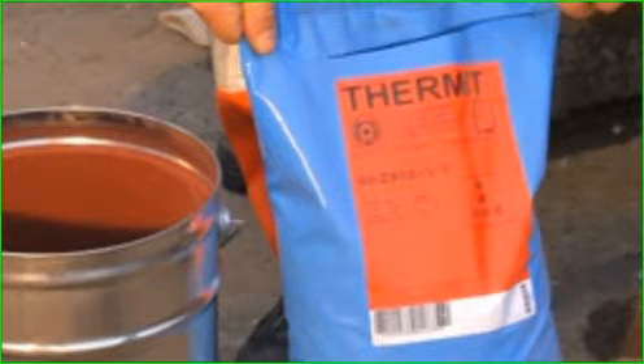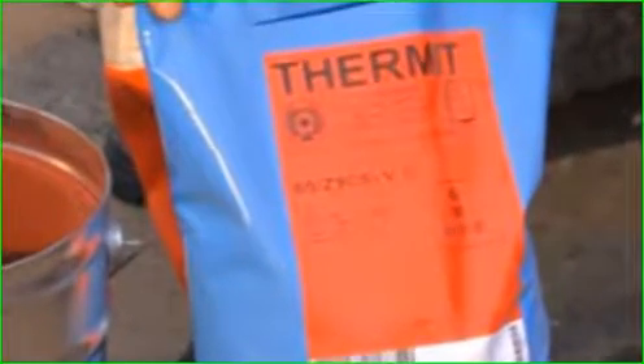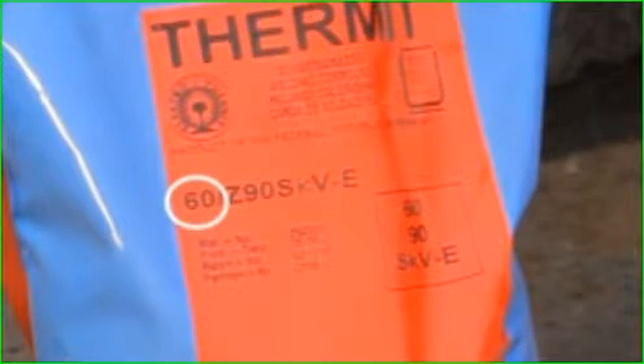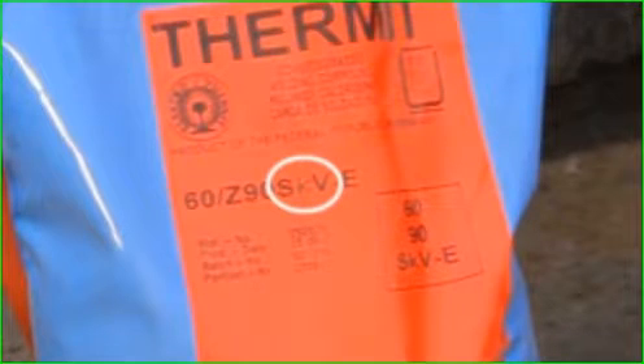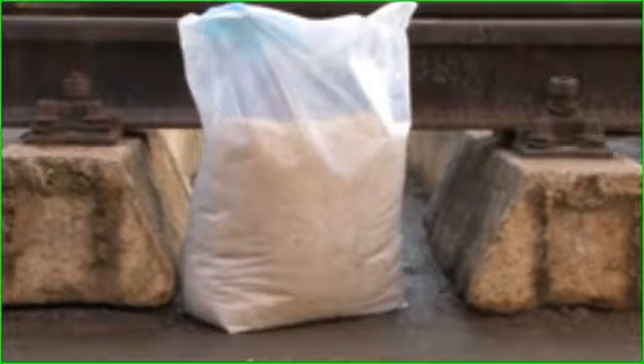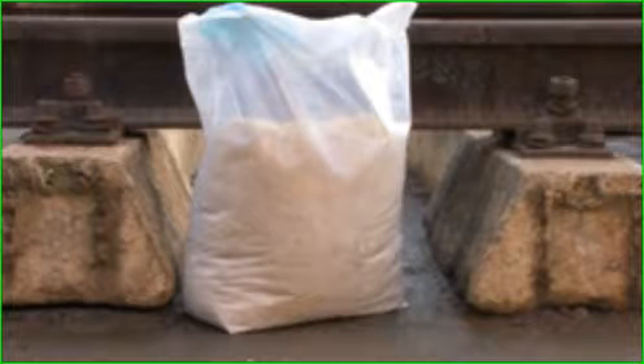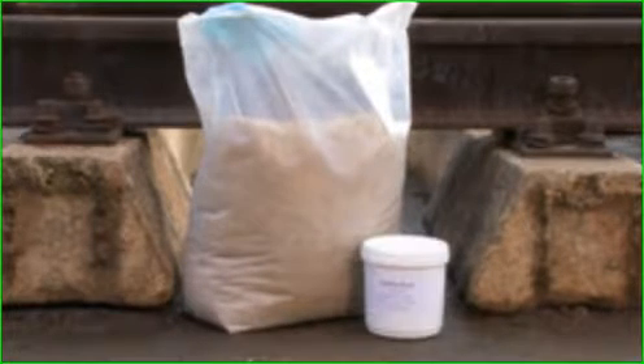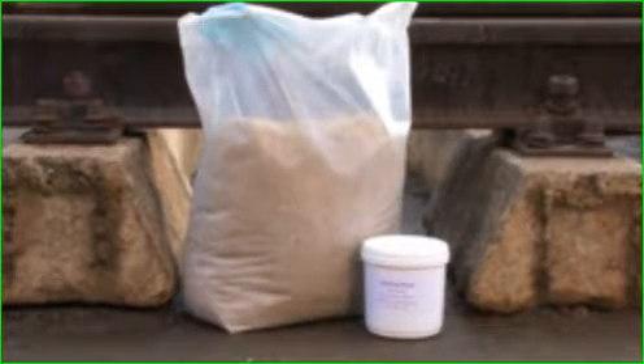By means of a chemical reaction, the thermit portion produces liquid steel. The thermit portion has to be selected with the help of its labelling, under the aspect of rail profile, under the aspect of rail grade, under the aspect of the used welding process, under the aspect of the selected crucible system. To avoid a split leakage of liquid steel between mould and rail, the area around has to be sealed either by using luting sand or by using luting paste.